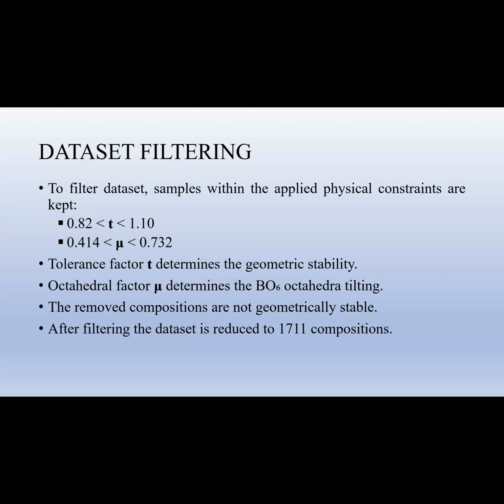For filtering the data set, geometric stability factors like tolerance factor and octahedral factor were used as physical constraints. So the perovskite samples having tolerance factor in the range 0.82 to 1.1 and octahedral factor in the range 0.414 to 0.732 were kept, and the samples outside this range were removed. The reason is that the perovskite samples lying outside this range were geometrically unstable. The removed compositions are not geometrically stable, so our retained data set only contains 1,711 stable compositions.